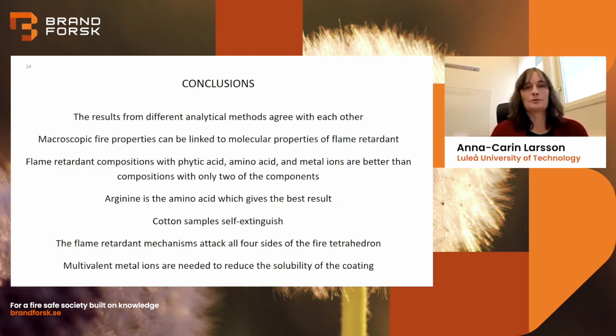So the conclusions we can draw is that the results from the different analytical methods that we have used agree with each other. The macroscopic fire properties can be linked to the molecular properties of the flame retardant. If we have compositions with phytic acid, amino acid, and metal ions, they are better than if we have compositions with only two of the components. Arginine is the amino acid which gives the best result, and cotton samples self-extinguish.